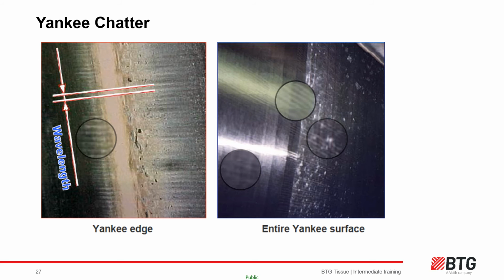If the chatter is limited to the outer layer of the cured coating layer, it can often be removed by additional use of the cleaner, potentially with a higher addition of release to strip the coating back, or even from a caustic felt wash. If chatter is deep in the coating, one way to remove it is to oil and doctor the cylinder to remove the coating layer and then apply a screen cloth or emery board under load for a few hours. The time will be determined by the severity of the chatter. You should replace the emery or screen cloth as it clogs up. The cylinder should then be remapped and reconditioned every time before starting up.